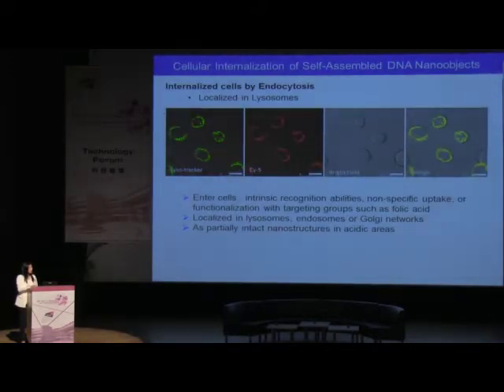So we recently found that most of the self-assembled DNA nanostructures enter the cell through intrinsic recognition properties, non-specific uptake, or functionalization with a targeting group. And most of them are localized in the acidic environment, such as the lysosome or endosome, and become only partially intact nanostructures. So this is not what we want. We want them to be stable and carry out their function immediately. So here we would like to introduce a new method to deliver them to the cytoplasm directly.